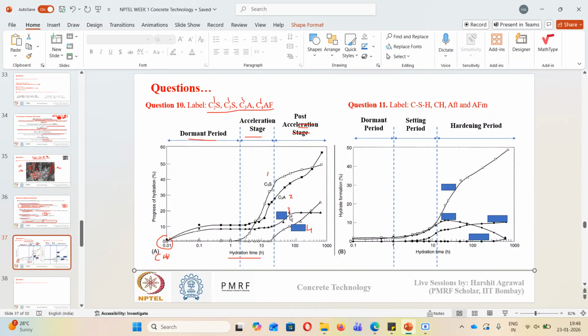Then this curve 3 that you see: the initial reaction was shown, then it becomes stable, again increases a little and becomes stable. That will be C4AF. Just like C3A, hydration for C4AF also occurs. And the fourth curve, which shows the reaction at very later ages, will be C2S. We know C2S is a slow reacting species, so it shows reaction at very later ages.